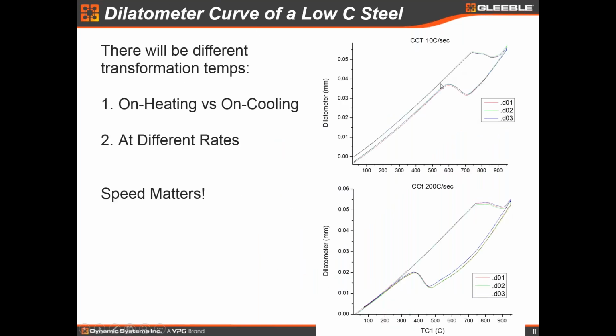So this shows, again, the same low carbon steel. This is a cooling curve at 10 degrees C per second and the cooling curve at 200 degrees C per second. So I believe these are probably heated at the same rate. So you see there's not a lot of difference in the heating curve here, but you can see a significant shift of the transformation temperatures on cooling to a lower temperature.